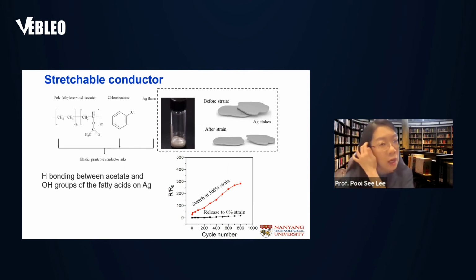So over here, the use of a stretchable conductor has to be considered if we're keen on developing wearable electronics. One of our earlier attempts was to use an elastomer with silver flakes, which does not give very good cycling stability and stretchability. It often leads to an increase in the resistance, let's say at 300% strain, as shown in the red curve over there. This is because the silver flakes tend to dissociate upon high stretching.